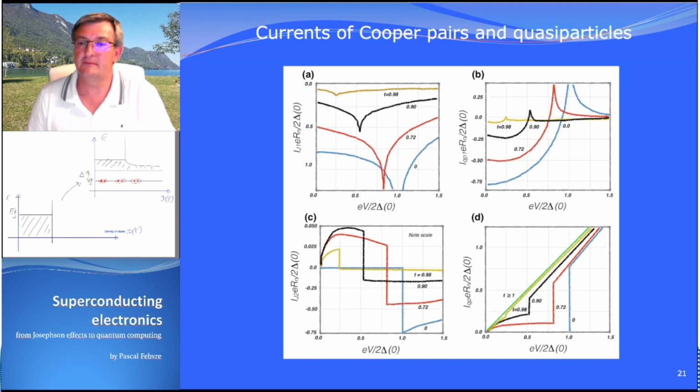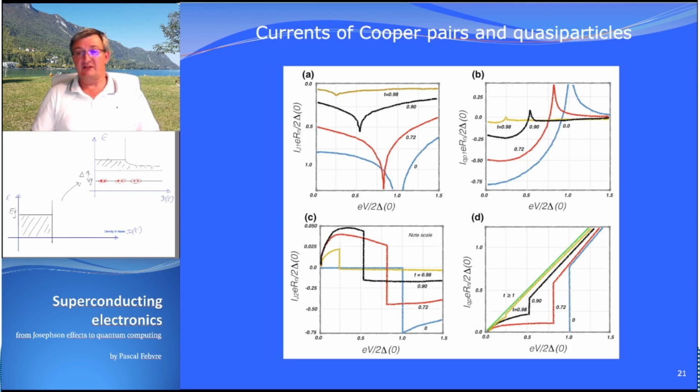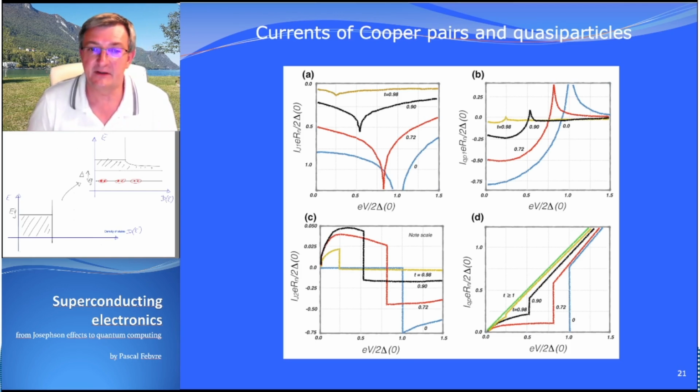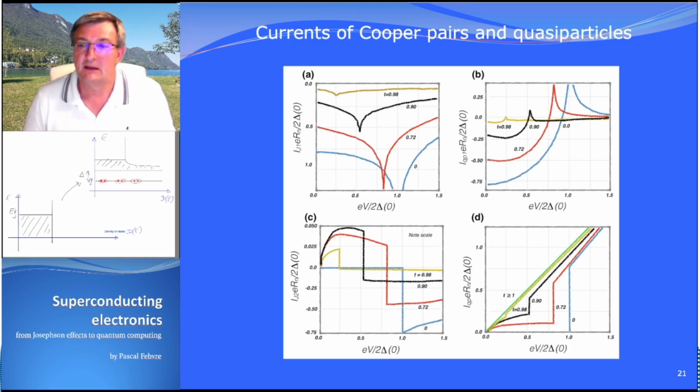This is the term that we usually use at any temperature, at least at Tc/2, because this is the dominant term of Cooper pairs, and you can see in particular an important property is that at 0 voltage the current is not zero, right? Which is one property of Cooper pairs and of superconductivity. You can have a current without voltage, so you can have a displacement without spending energy because the voltage is zero. And you have this evolution with, of course, a feature at the gap energy.